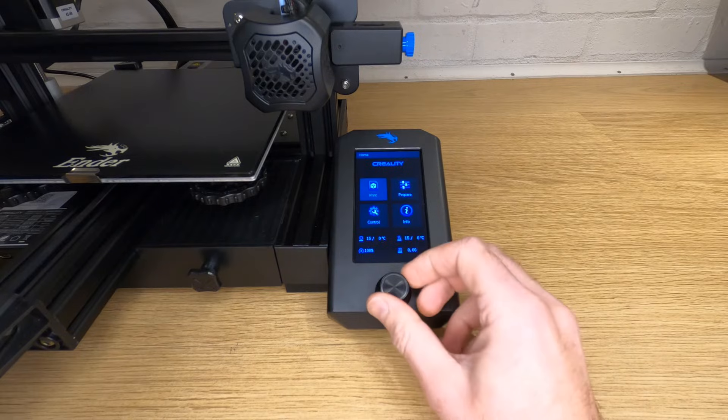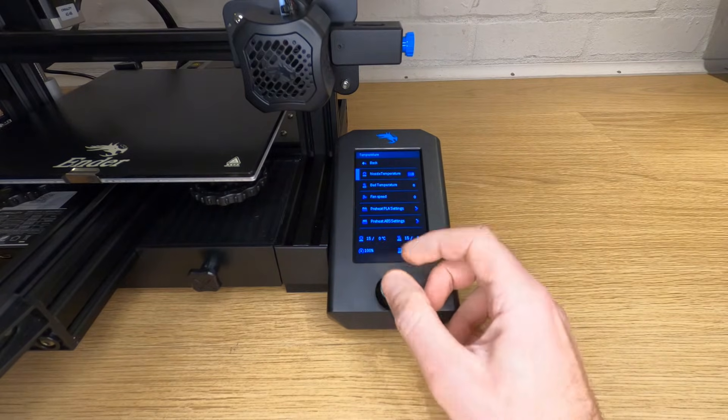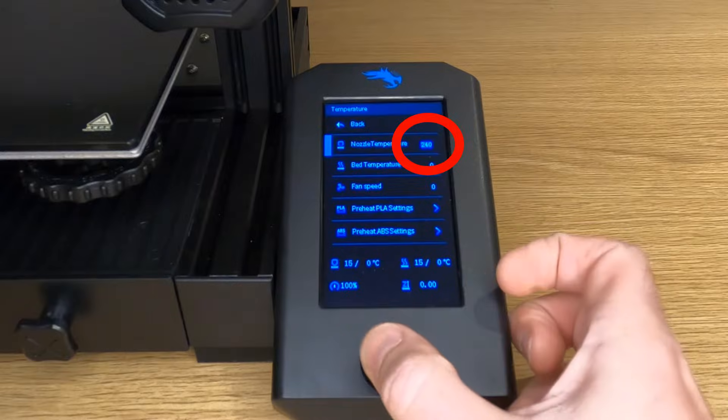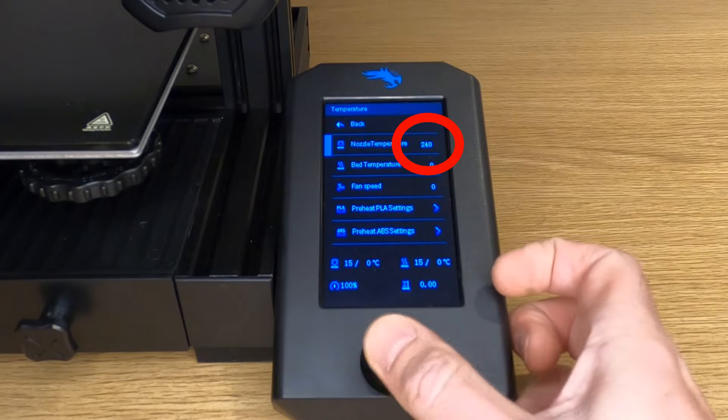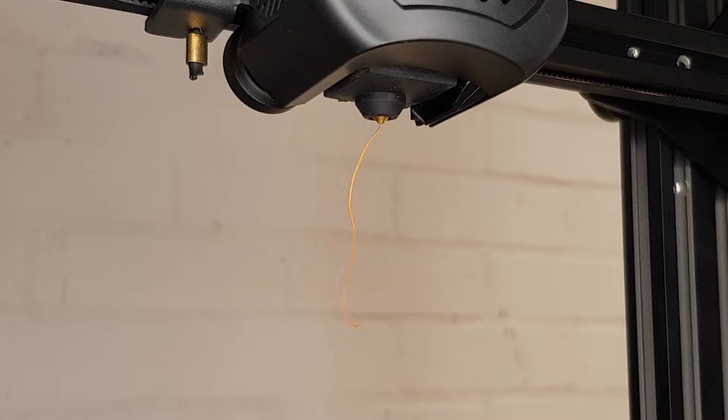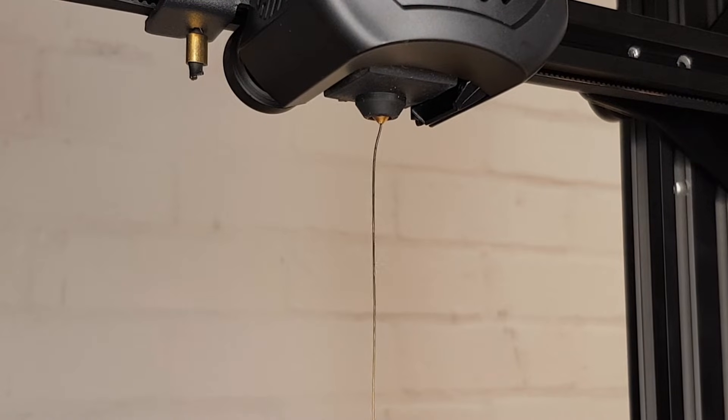Now warm up your hot end not just to the melting temperature of this filament but to just above the melting temperature of the previous filament you used. Why is this important? Well imagine you were last printing with something with a higher transition point like PETG. Unless you've thoroughly cleaned the nozzle and hot end, there's going to be a little bit of that plastic left behind in the nozzle. If you don't heat the hot end up to the transition point of this material, then it's never going to melt and pass through the nozzle when the new material pushes in behind it.